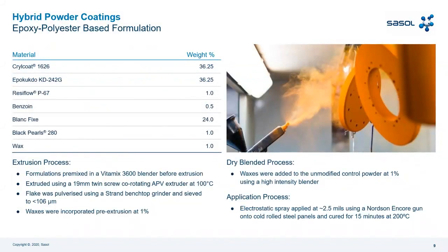So, overview for the first test. We tested the first technology, hybrid powder coatings, epoxy-polyester based formulation. Here we have a base formulation, a standard formulation. As I mentioned before, Sasol makes all these tests in cooperation with an independent external institute that suggests a standard formula with an amount of wax of 1%. That is the standard one.